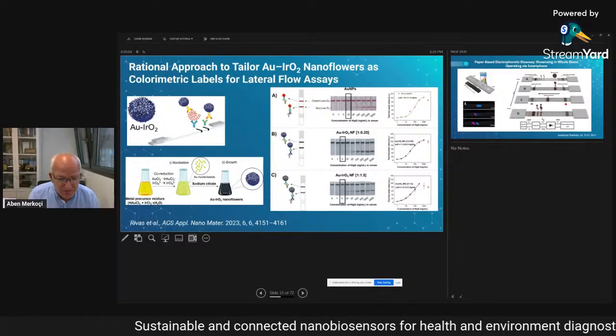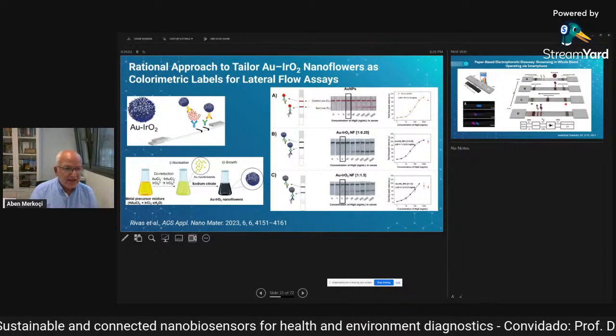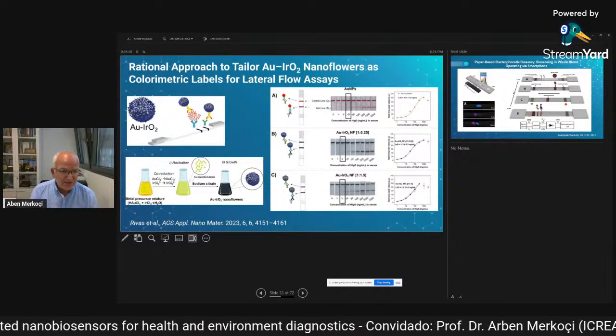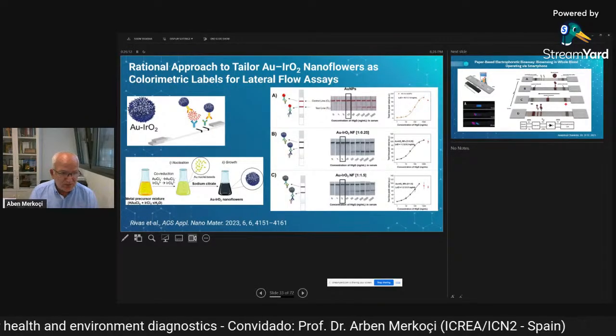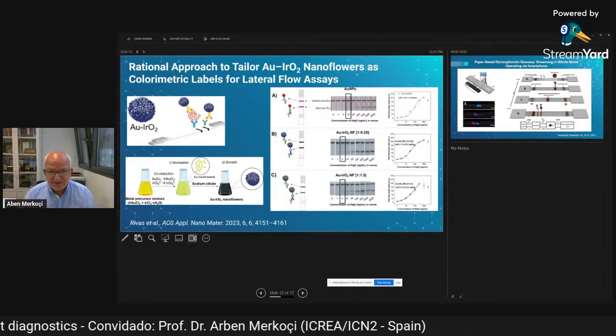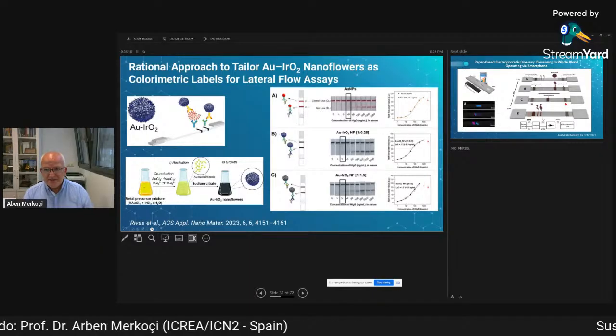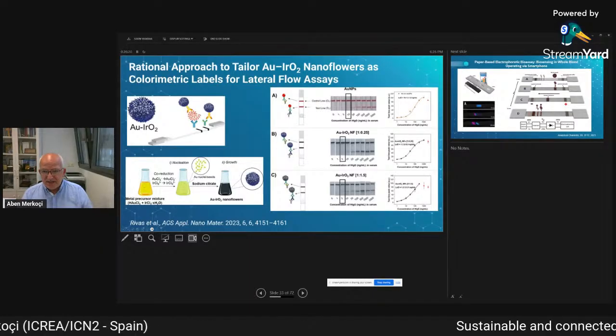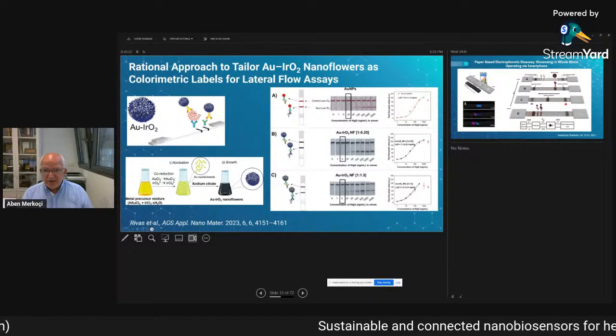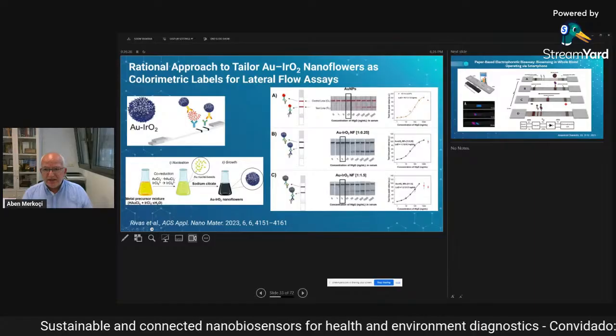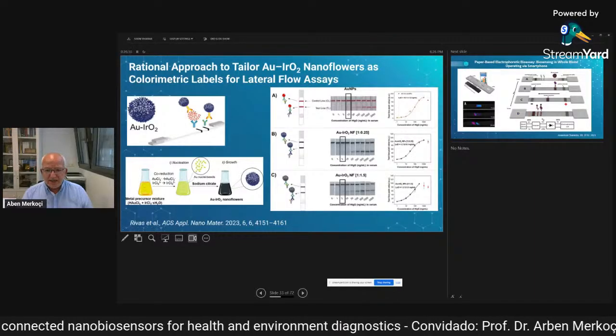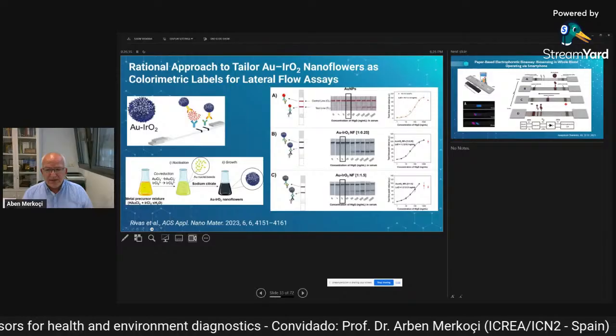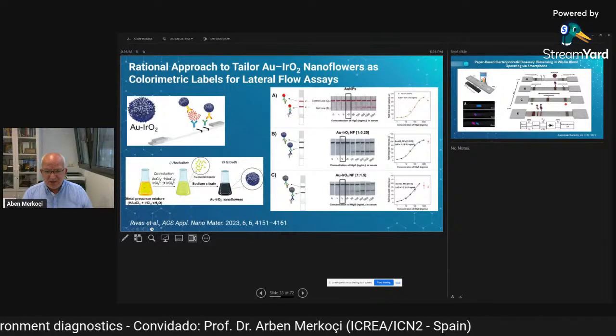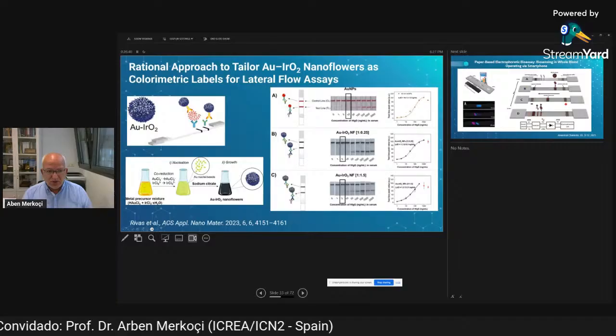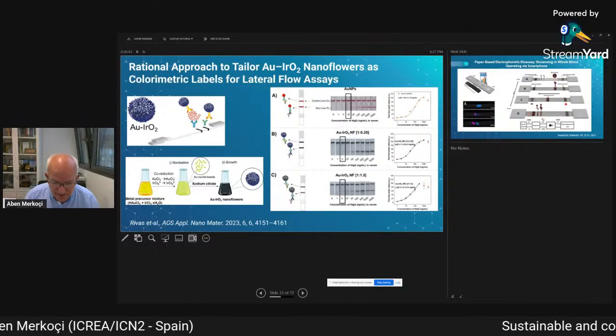We also have been working with different kinds of nanoparticles. This is a case in which we try to increase the signal by using iridium oxide nanoparticles combined with gold in a way that, as you can see, for example, the standard gold nanoparticle based assay is able to detect up to 10 nanogram per milliliter human IgG, while we go down to 3 nanogram per milliliter in case of using of gold iridium oxide nanoparticles in different concentrations. So this is very, very interesting to get higher sensitivity.